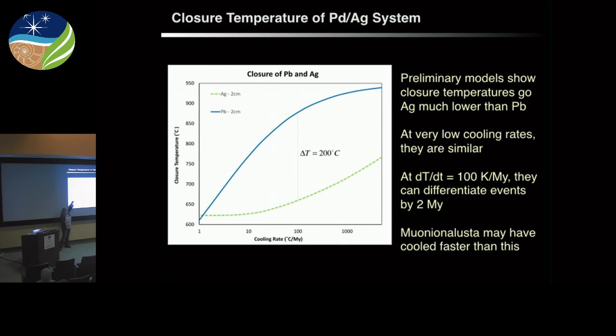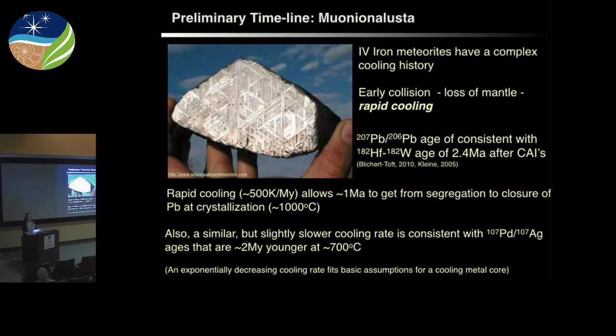This is our lead closure temperature. So at high cooling rates, such as what we expect in the IVA iron meteorites, we're up around 900 degrees Celsius. And here's the palladium-silver closure temperature. It's a couple hundred degrees cooler, maybe around 700 degrees Celsius, right? So they're separated by 200 degrees, which if you're cooling at 100 degrees per million years is 2 million years in time. So that information might be able to be used to disentangle some of the overlap or confusion between some of the ages that have been measured in iron meteorites, particularly the IVA iron meteorites.